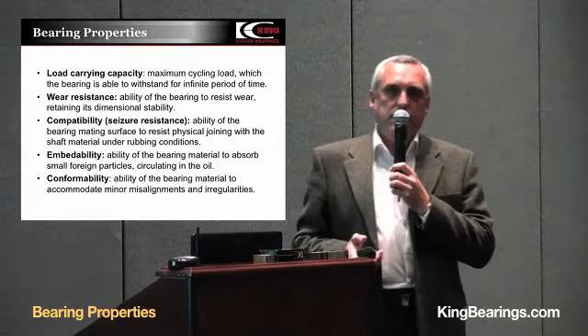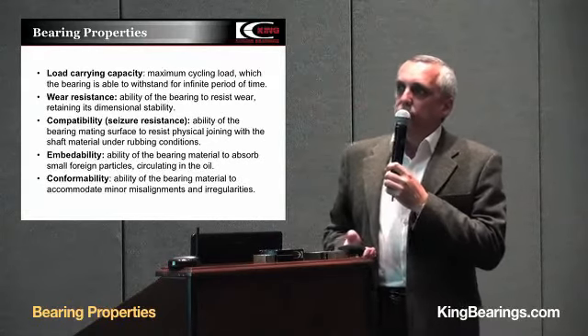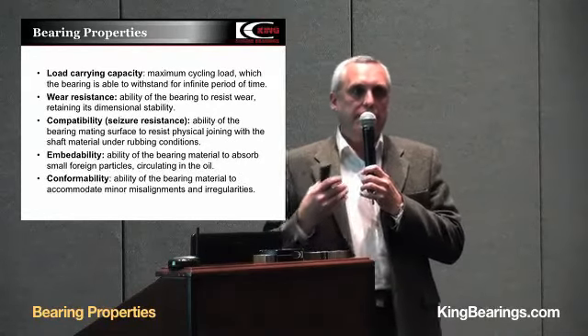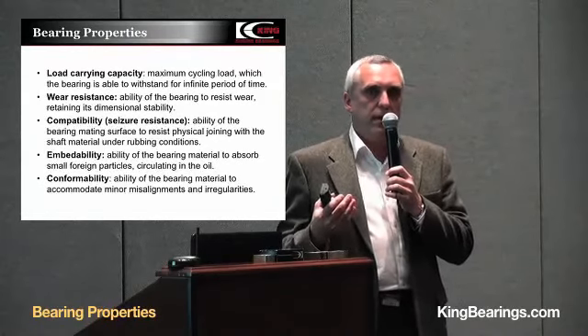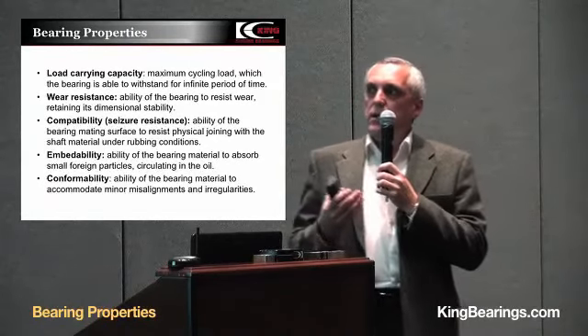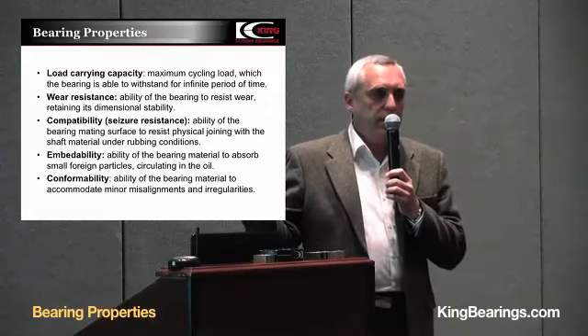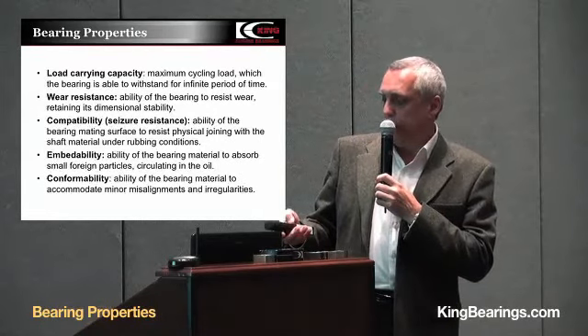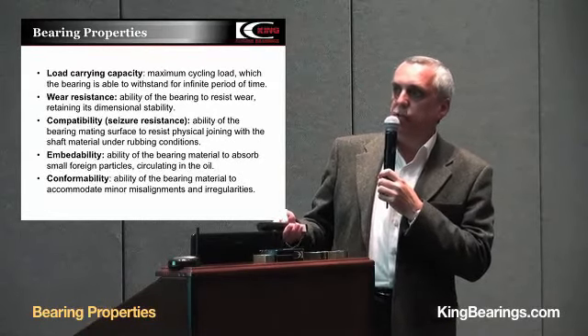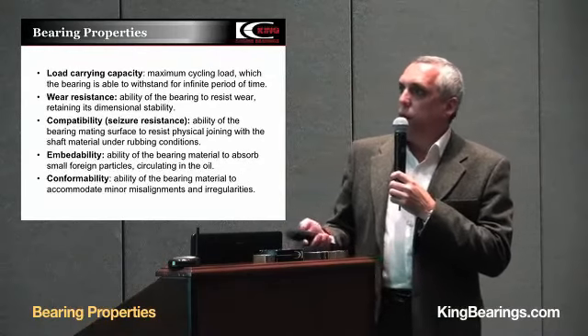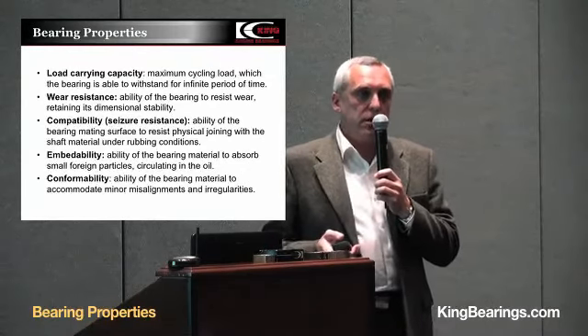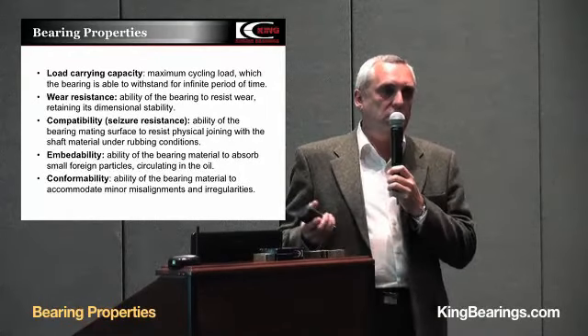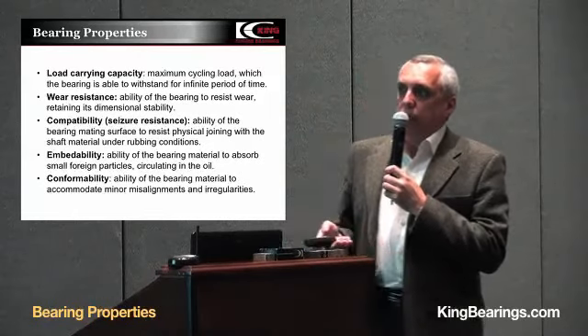Compatibility, or seizure resistance. This is the ability of the bearing mating surface to resist physical joining between the bearing material and the shaft material. It may cause adhesive wear, as we saw in the previous slide. If the compatibility is low, it may cause seizure between the bearing and the crankshaft and shutdown of the engine.